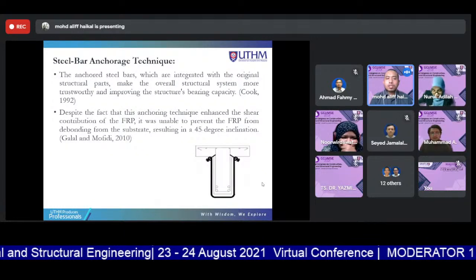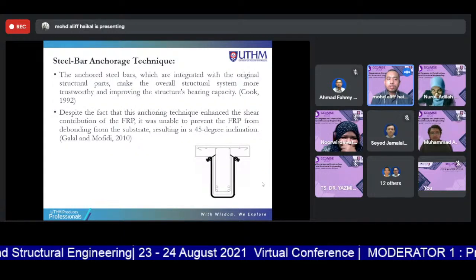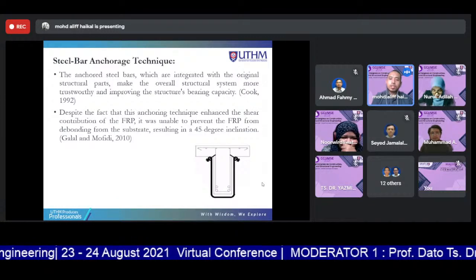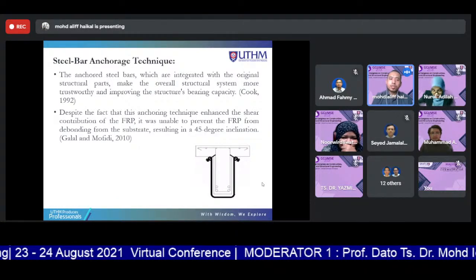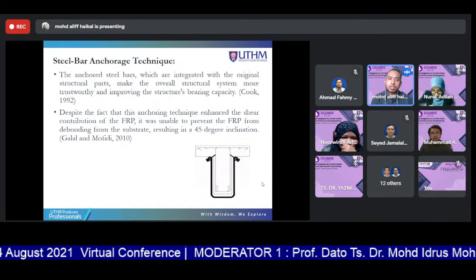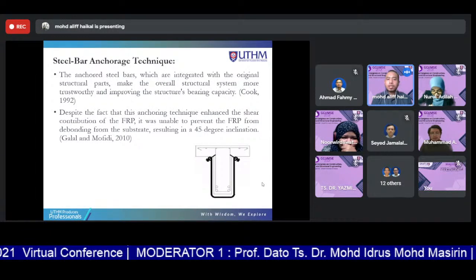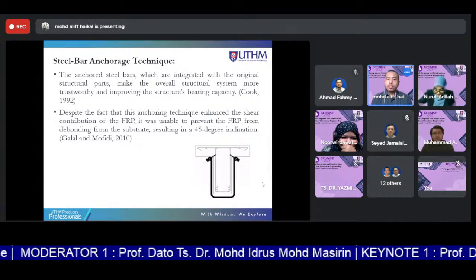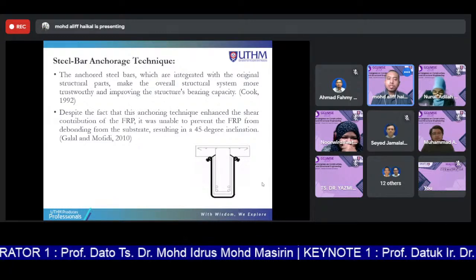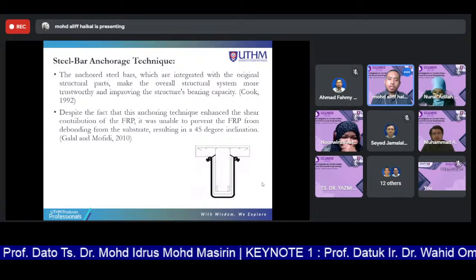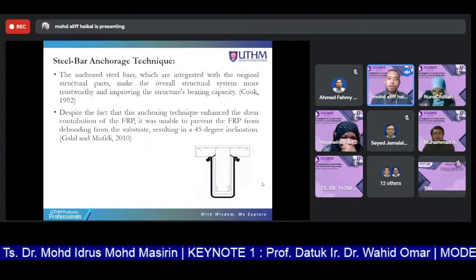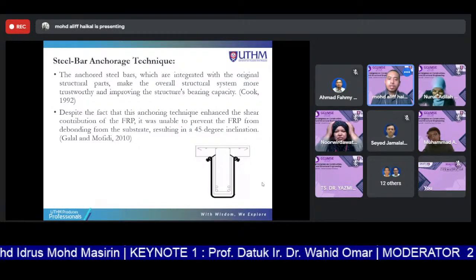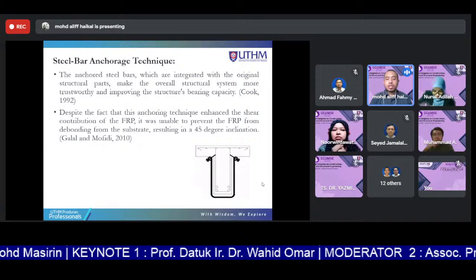And then there is the steel bar anchorage technique. The anchored steel bars, which are integrated with the original structure, make the overall structure system more trustworthy and improve the structure's bearing capacity. Besides the fact that this anchoring technique enhanced the shear contribution of the FRP, it was unable to prevent the FRP from debonding from the substrate, resulting in a 45-degree inclination.